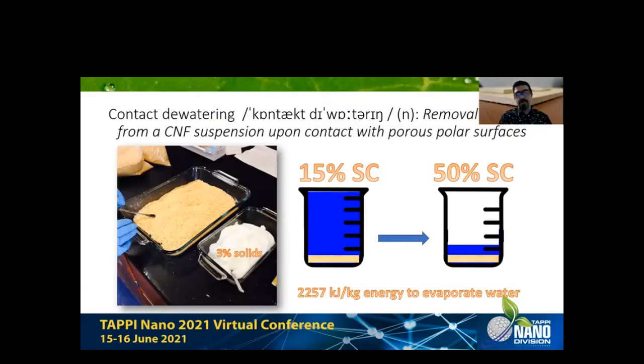The biggest issue for that actually is water. So we know that nanocellulose is produced in water. In this case, there's a 3% solid CNF, and you have here wood particles, the same wood particles that are used to produce particle board. If you mix these two together at the ratio of 15% dry basis of this and 85% dry basis of the other one, you end up having a mixture of about 15% solids content. If you take a small amount of this nanocellulose in your hand and try to squeeze the water out, you can't do that. It holds tenaciously to water. It's very difficult to do that.